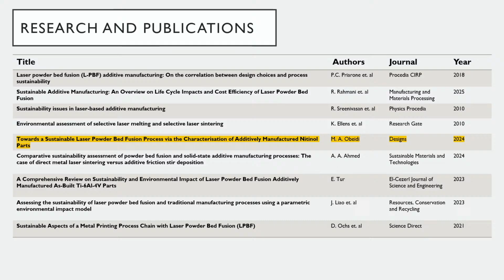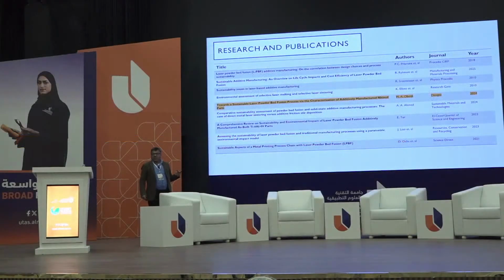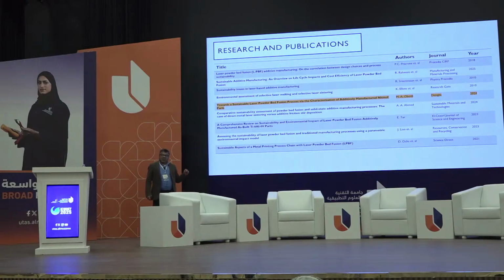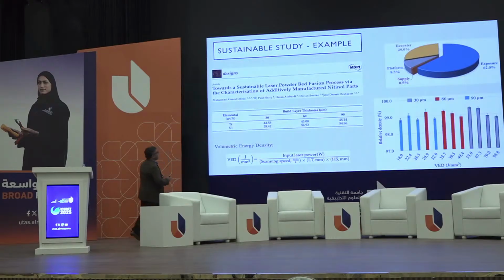My output measure was two things: density. My goal is to achieve the higher density, closer to the full density, so that I can say, okay, it's close to the cast material. And number two is the chemical composition. Again, once I melt material, I want to maintain the chemical composition as the raw material, which is the powder.